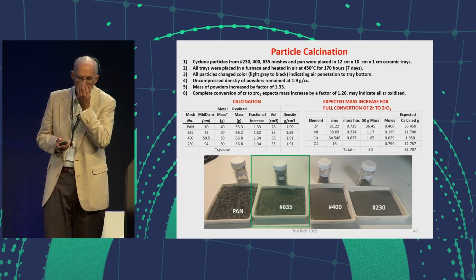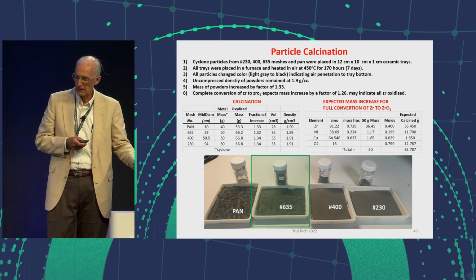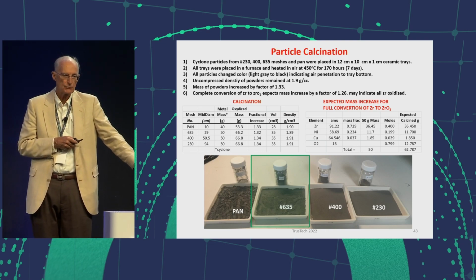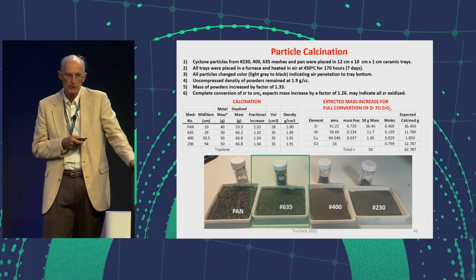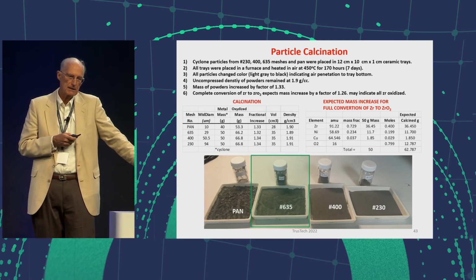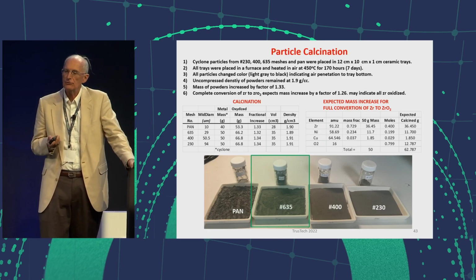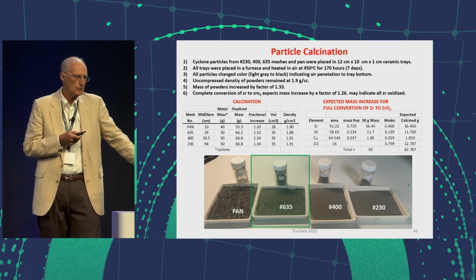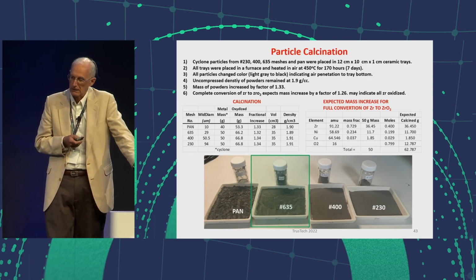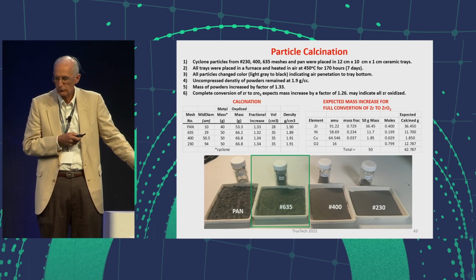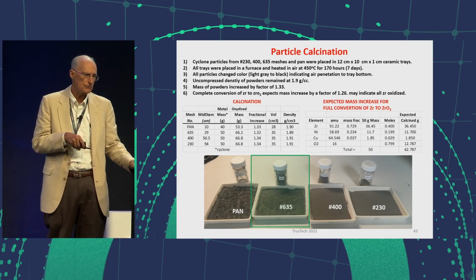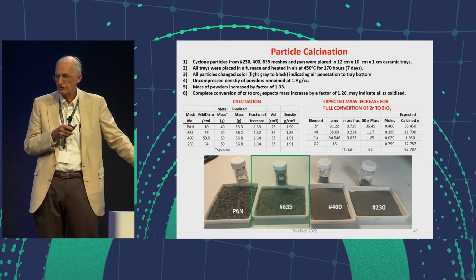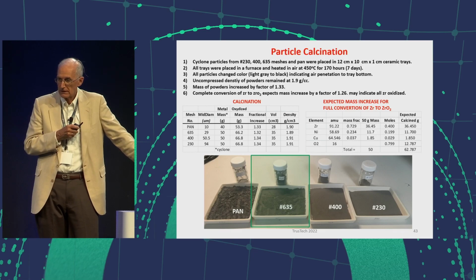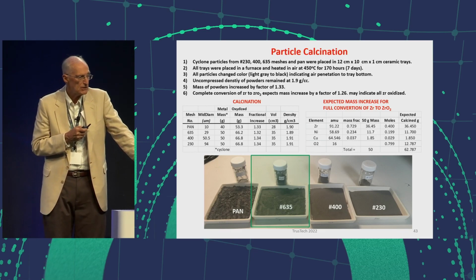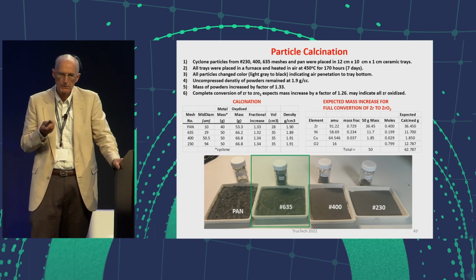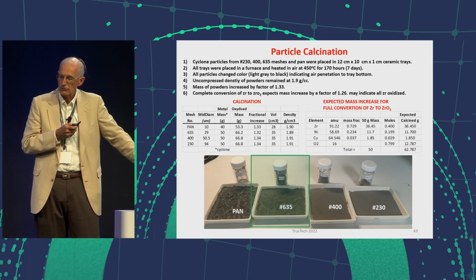So for the processing of these particles, I took 4 ranges of particles and I put them in trays. And these trays I put in a furnace. And following the prescription by Technova, I calcinated these in the furnace for 7 days at 450 degrees C. The particles were about 1 centimeter thick. I didn't know whether the oxygen from the air would reach the bottom, but I was happy to see that basically all the particles changed color, top to bottom, from light gray to black.